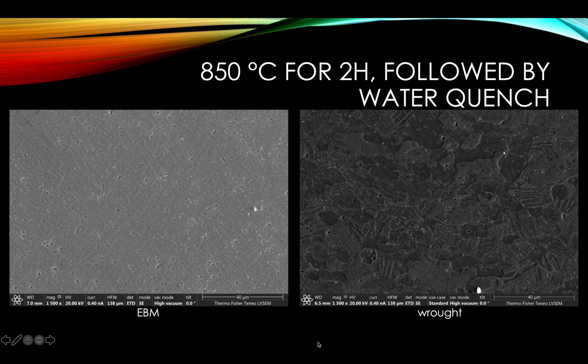For the 850 Celsius followed by water quench, the EBM sample doesn't show much contrast under the SEM. This can indicate that the plate-like beta phase forms. You can also see lots of these globular grains within the beta plate. This can indicate an incomplete transition from the beta phase to the alpha phase. Well, for the wrought sample, the grains are becoming less uniform, and the shape is kind of rounded, not very pattern-like, and however the grain size doesn't change much.